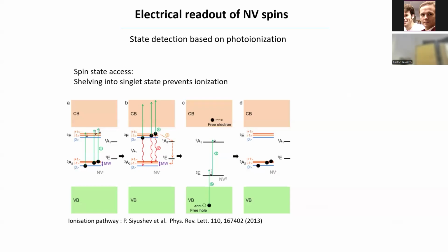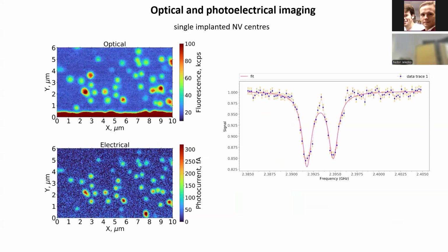And if you have a voltage across the area with your NV center, you can detect these electrons and holes, measuring the spike in photoconductivity. So that's an additional channel to detect color centers. And because your photoionization happens via the excited state, it carries all the information that the excited state population carries too. It has all this spin contrast, very similar to the one coming in photoluminescence.